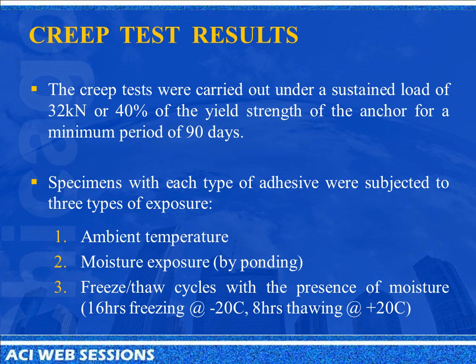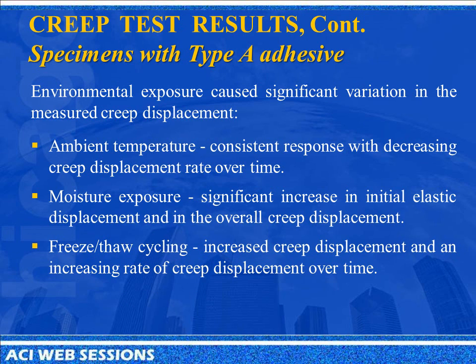The three exposure conditions that we used: the ambient temperature, moisture exposure, which was achieved by ponding, and freeze-thaw cycles with the presence of moisture because of ponding as well. The freeze and thaw cycles were cycled per 24 hours, 16 hours of freezing at negative 20 Celsius, and 8 hours of thawing at plus 20 Celsius. The test results for specimens with type A adhesive, so again, that's the fast-setting acrylic-based adhesive. Under ambient temperature response, we got consistent response with a decreasing rate of creep displacement over time, while when exposed to moisture and freeze-thaw, we see an increase in creep displacement and a bit of inconsistency as well.